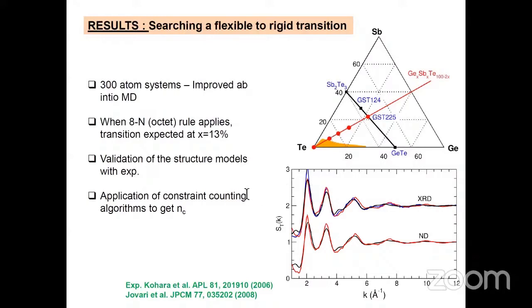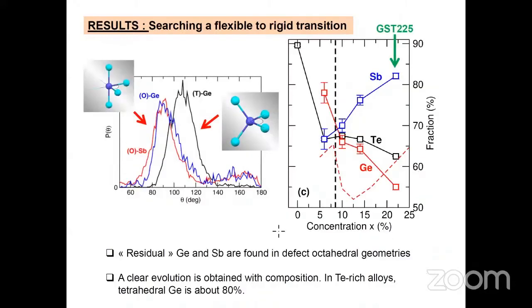So we first validated the structure models from our ab initio simulations. Here's an example, a comparison with X-ray or neutron diffraction results. And then we applied a constraint counting algorithm to get the fraction of constraints. We have just seen how we calculate angular constraints from the tetrahedral fraction. So the result is shown here.